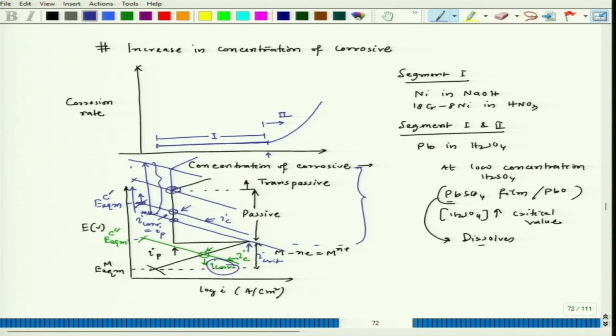high concentration of H2SO4. Now there could be one more pattern that is possible. Initially it gradually increases the corrosion rate as the concentration of the corrosive increases, and then suddenly it drops, and then it maintains a constant value. Okay. So this kind of pattern can be observed. Let us say this is pattern A, and let us say this is pattern B. In pattern A, we have two segments. One segment we have seen in nickel in NaOH or 18-8 stainless steel in HNO3, and pattern A with the segments 1 and 2, Pb or the lead in H2SO4 can follow that.